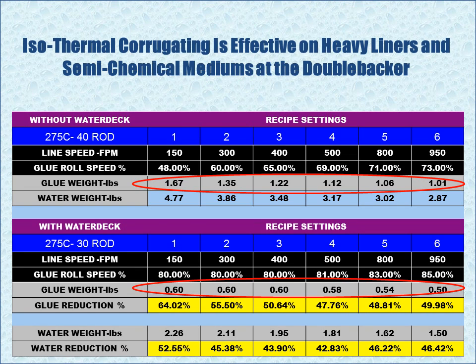An isobar glue machine used with a typical corrugator can reduce starch consumption considerably, as we can see here. But look at the performance of the isobar glue machine on an isothermal corrugator. The glue line stays flat over the entire speed range, and you can even taper it off a little more at higher speeds. Water reduction, the total amount of water reduced in the process, varies over the speed range from about 52% at the lowest speed to 46%. Glue reduction varies from about 64% down to 50% over the speed range.